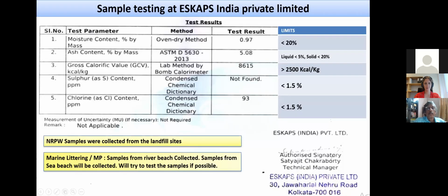Thank you, Shouro. Now we will discuss the testing carried out on the waste plastic collected from the different dump sites. So we have tested plastic samples from different dump sites at 2 different testing laboratories. The compulsory testings for AFR to be co-processed are our main focus of testing. That is moisture content, ash content, gross calorific value, sulfur, and chlorine content.